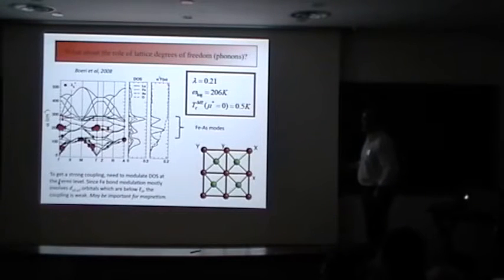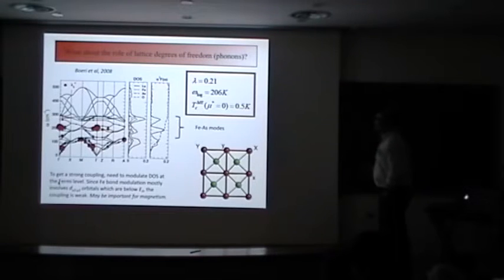In terms of the role of the lattice in the pnictides, early on it was established that the electron-phonon coupling can be connected to the mixed vibrations in iron and arsenic, sitting around the 200-300 wave number energy range. But the lambda that comes out is 0.21, which is not very strong. If you take a Debye frequency to form your superconductivity, you find that's just not strong enough, not enough juice to provide the strength to form a superconducting state.